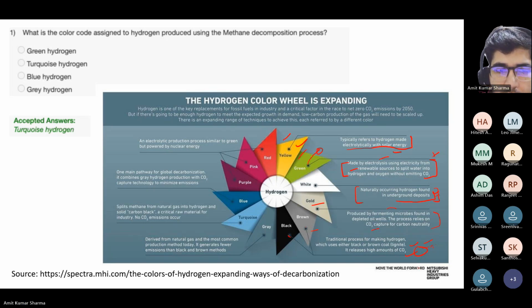Gray is derived from natural gas using steam methane reforming, or the different kinds of reforming we have discussed. It is the most common production technique; I think more than 50% of the world's hydrogen today comes from steam methane reforming, and that is gray hydrogen. It generates fewer emissions than black and brown methods. The emission is around 9 to 10 kg of CO2 per kg of hydrogen. For brown it is around 14 kg of CO2, and for black around 19 kg of CO2 per kg of hydrogen.